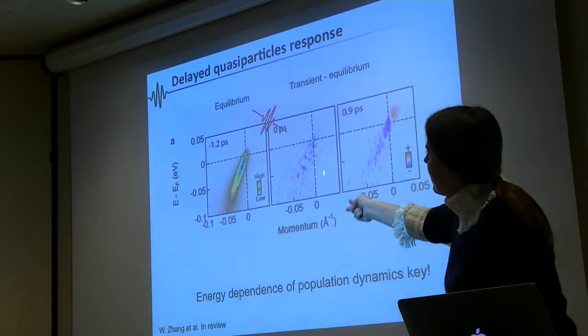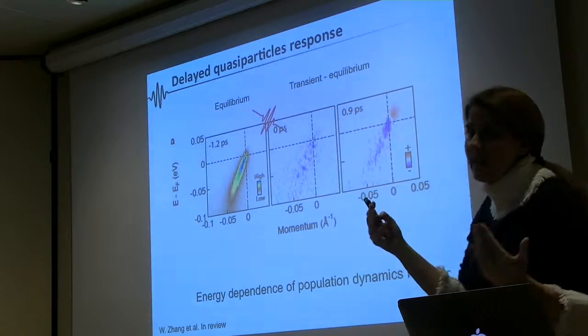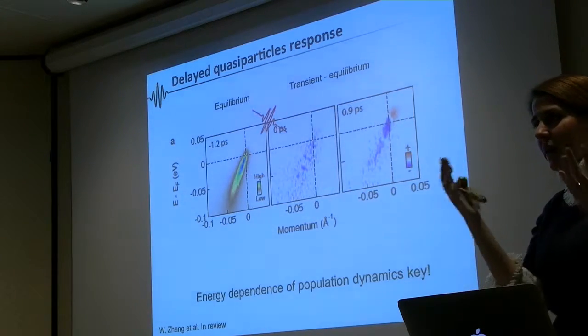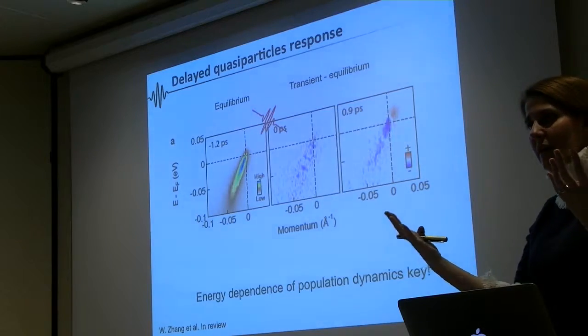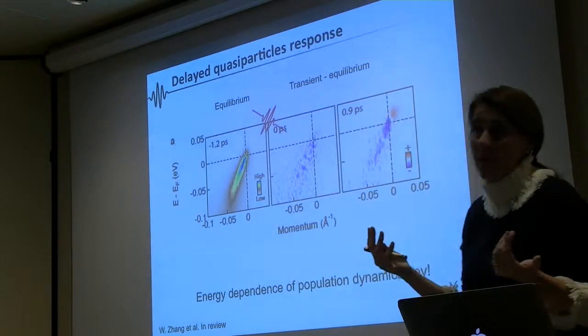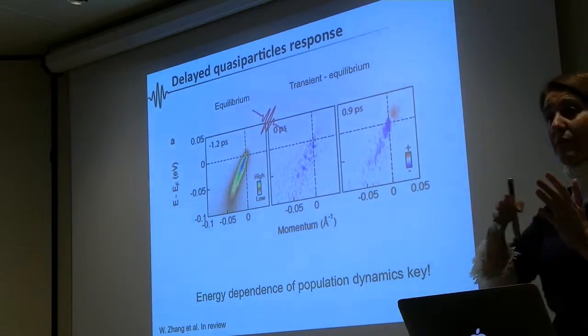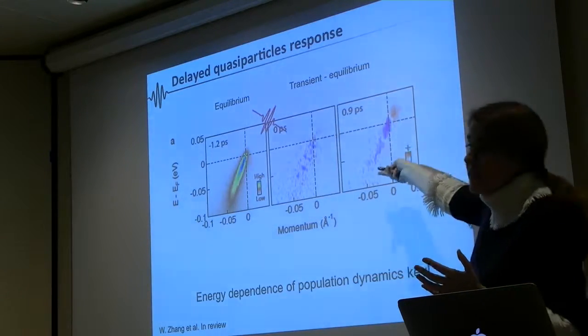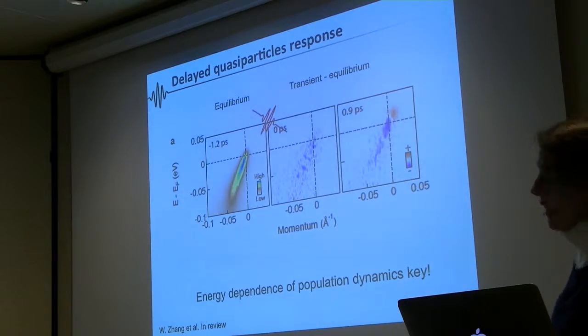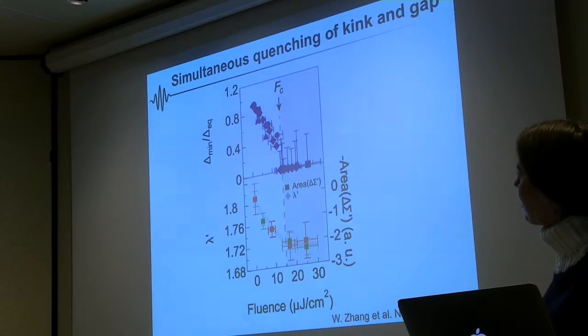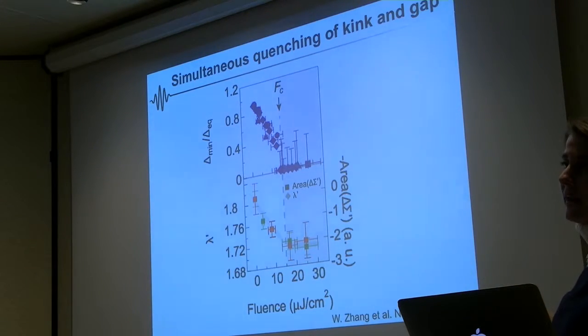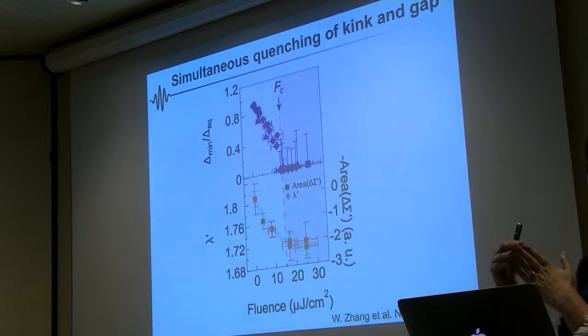So you see here that the difference is almost 0. Meaning that even if I came in with a pump, the non-equilibrium state I created is almost the same as the equilibrium, which is telling you that it's like there would be a delay. And when you go down here, now you see that there is a big difference. And so, in conclusion, pretty much, we can look at the time scale associated with the electron-phonon coupling, and we